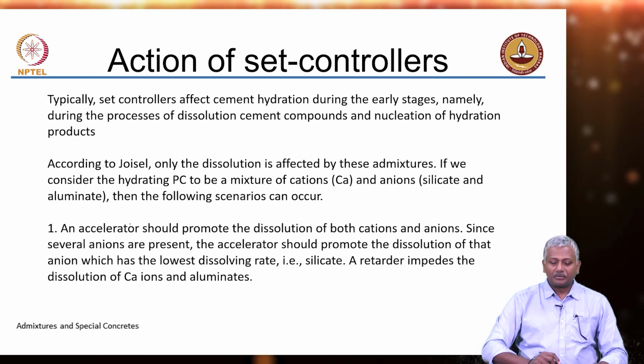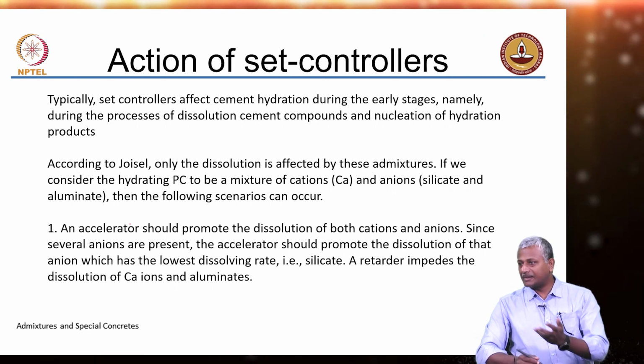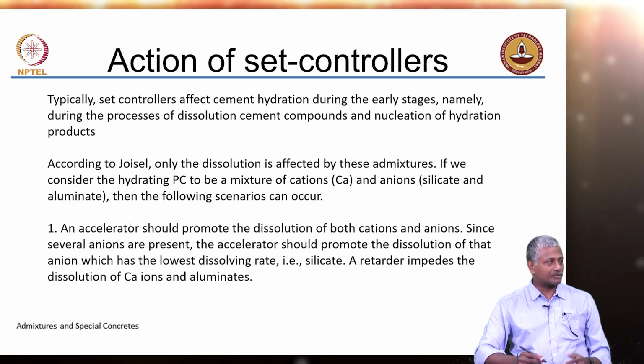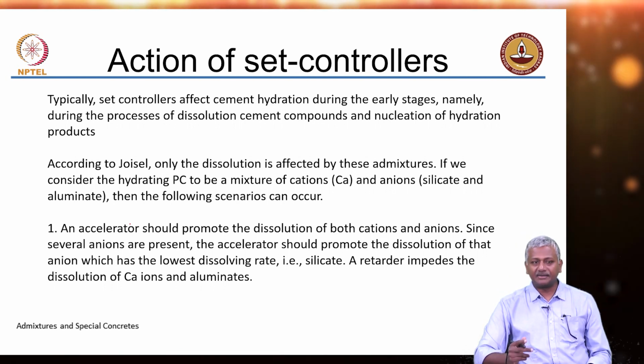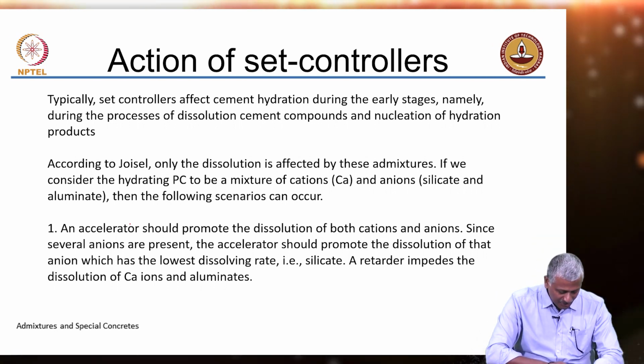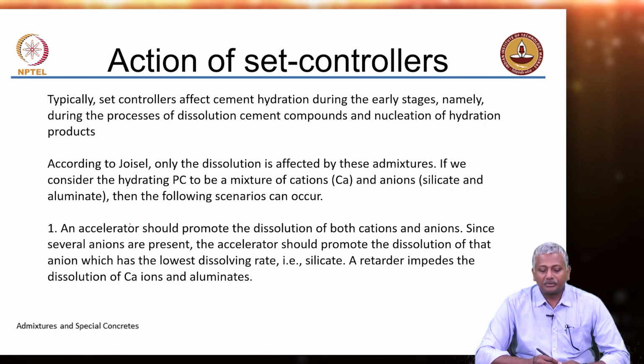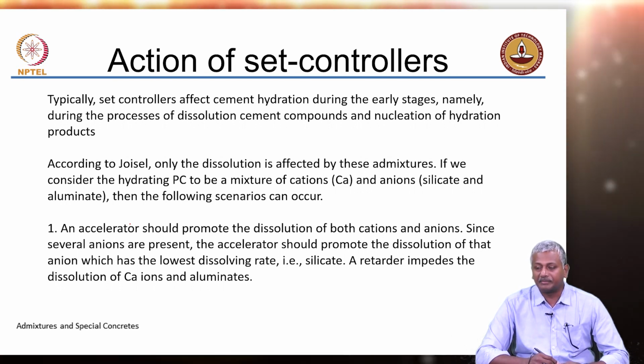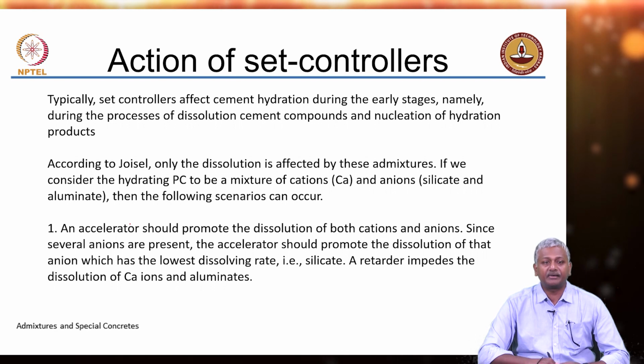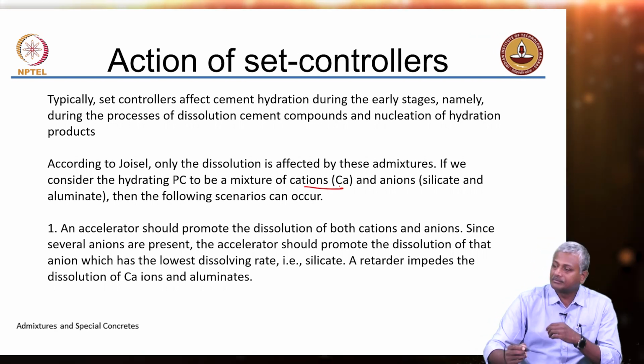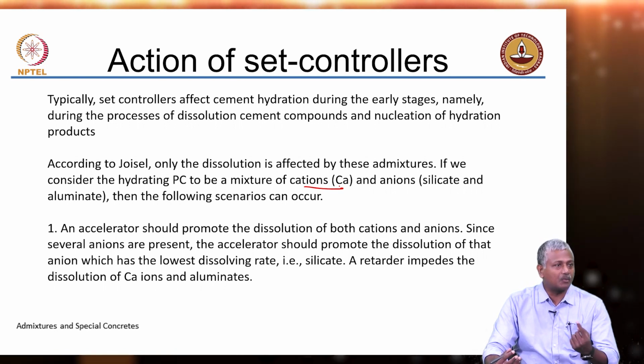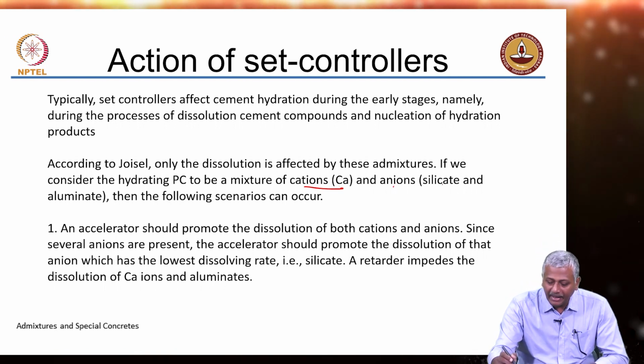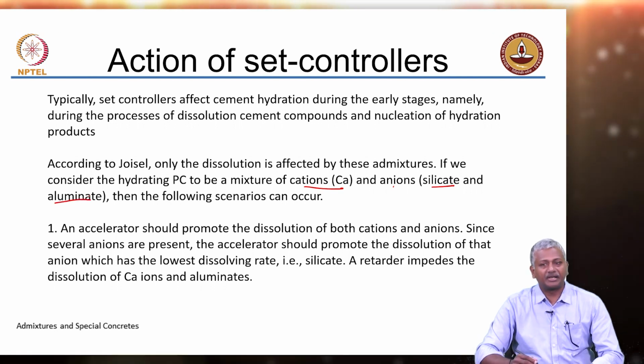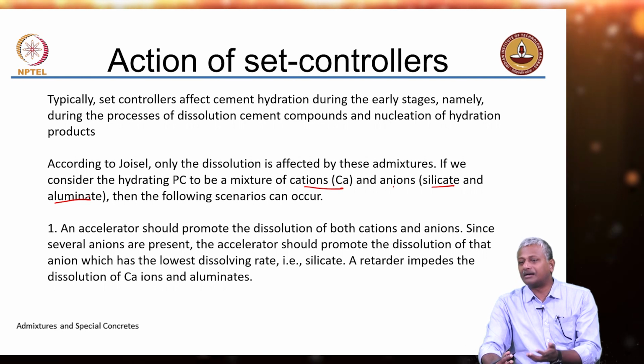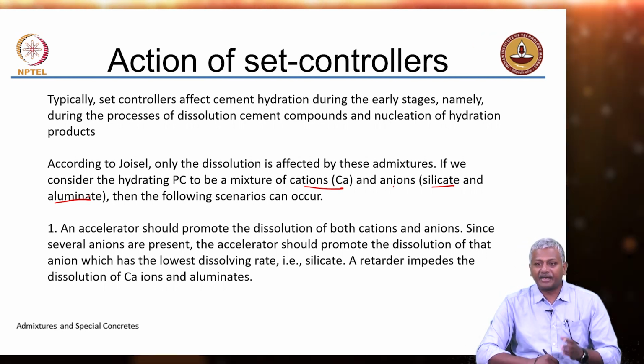Now, it is interesting to note that certain types of chemicals behave both as retarders and accelerators. So, we need to understand what the chemistry is. As I said, the primary effect on the cement chemistry is during the dissolution process of the cement hydration. Another scientist named Joisel said that the dissolution is affected by these admixtures if we consider the hydrating Portland cement to be a mixture of cations and anions. All the compounds are calcium based, so there is only one cation, that is calcium, and anions, either silicate or aluminate. Let us not even consider C4AF in the system, because that is hardly reactive, it does not react much at all. So, you have anions which are silicate or aluminate.